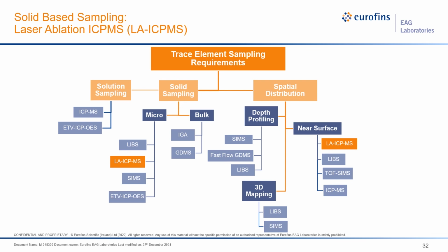an ICP-MS, where it is ionized and analyzed for its elemental constituents, just like solution-based ICP-MS, but without the digestion preparation step. And instead of synthetic standard solutions, laser ablation ICP-MS requires the analysis of matrix-matched solid reference standards alongside samples for quantification. And in fact, EAG has thousands of solid reference materials for this very purpose.